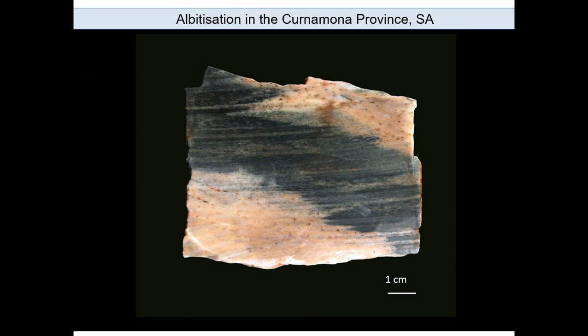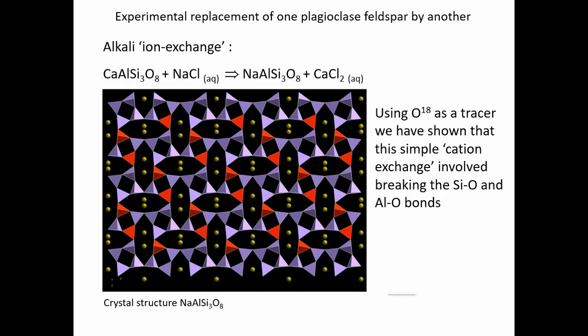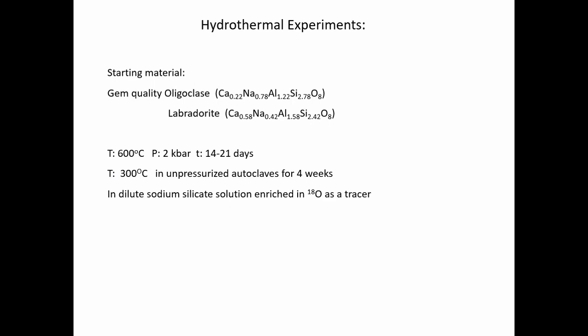But we've reproduced these kinds of experiments in the lab. If we have a feldspar structure, we've also used oxygen-18 to trace the water, because it's a fantastic way of finding out where the oxygen is going. We could say this is a substitution experiment, that we're taking out the calcium, for example, and putting sodium in the structure. Very simple ion exchange. Solid state diffusion, probably. So these are the experiments that we did with the starting material. We did it both with oligoclase and with labradorite, but here's the first one with oligoclase. There's the composition. The experiments were done at 600 degrees and at 300 degrees in pressurized autoclaves.